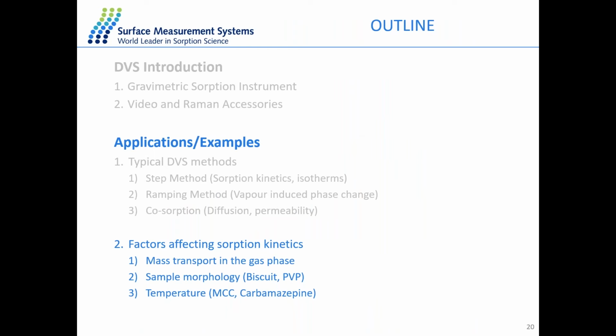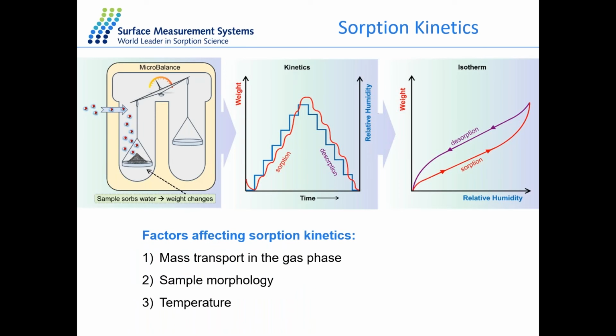And the last part I will talk about today is the factors that will affect the sorption kinetics. So with the DVS technique, we can change the environment condition of the sample inside the chamber here. And then we weigh the sample to reach equilibrium at each step. From the equilibrium mass, we can then plot this isotherm. So the mass plot in the middle here will give us the kinetics information about the moisture sorption and desorption, just how quickly the sample is picking up the vapor and how fast the sample mass is reaching equilibrium.